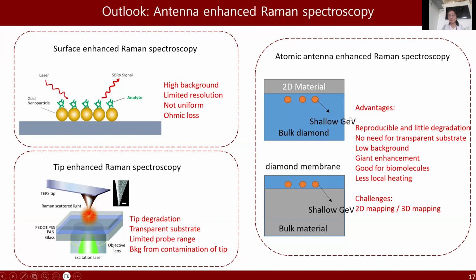This method has a lot of advantages. For example, since it's just single atoms, there's little degradation and it's very reproducible. The power that is required to activate the GeV antenna is nanowatt level, so it will have much less optical background noise. Also, diamond is a material that is compatible with many biomolecules. There are also some challenges for sure. For example, if we want to do a Raman mapping, we need a very high density of GeVs. This can potentially damage the diamond lattice and cause some decoherence.